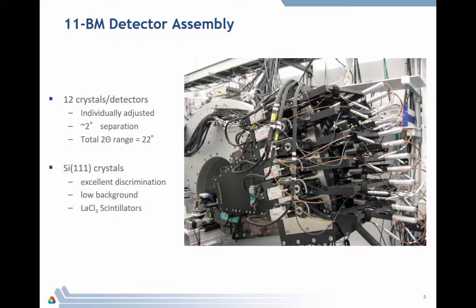In front of each of these detectors, we have a silicon analyzer crystal which is aligned, as was mentioned in earlier talks, so that only x-rays coming from the sample satisfy the Bragg condition. This will bring down the background and improve your resolution. It does have a downside, which is you're throwing away flux. Everything you do to improve resolution generally throws away flux. Same like if you want to reduce your background, you're doing that by throwing away flux.